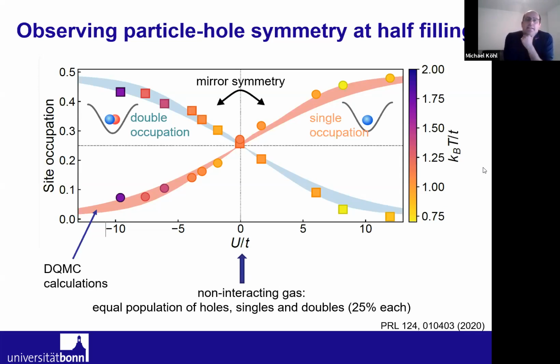And what you then see is that if we go to repulsive interactions, which is the right-hand side of this graph, of course, the amount of single occupied sites goes up because it costs interaction energy to have doubles, and the amount of double occupied sites goes down accordingly. If we're at 0, we have 25%, that's just statistical. And if we go to the attractive side, of course, we get more doubles because the particles are now attracted towards one another, and we reduce the amount of singles. And this is perfectly mirror symmetric about this U equals 0 point. And that is the first indication that this particle-hole symmetry actually works.